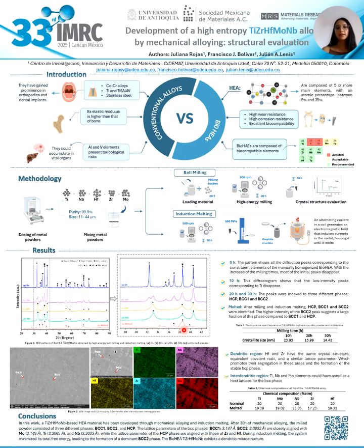This indicates that during induction melting, the system reduced its total free energy, leading to the formation of a dominant BCC2 phase.